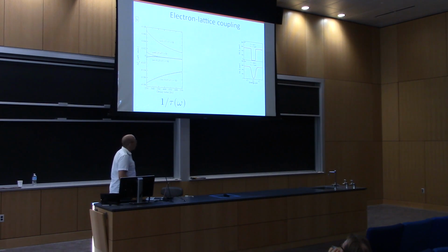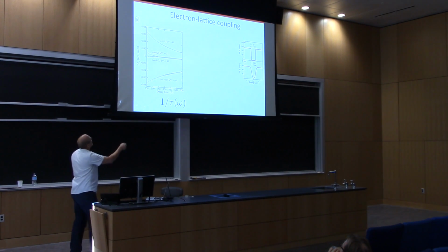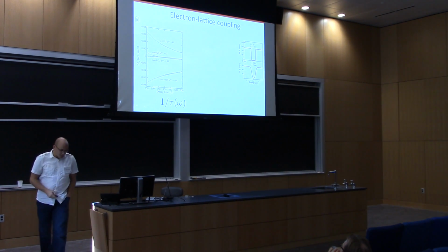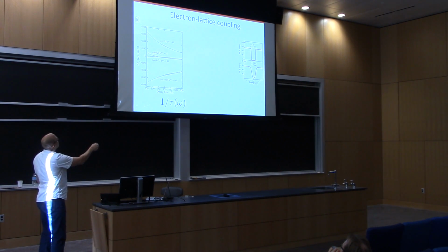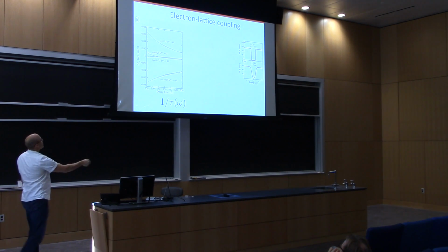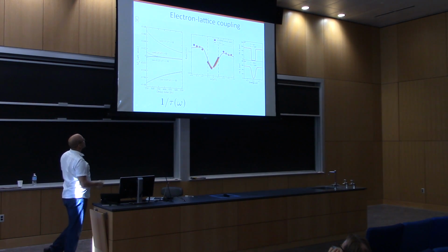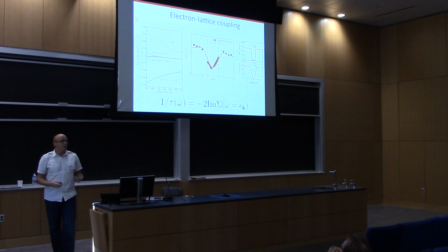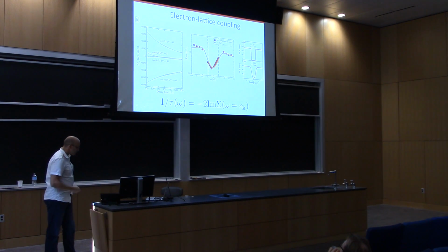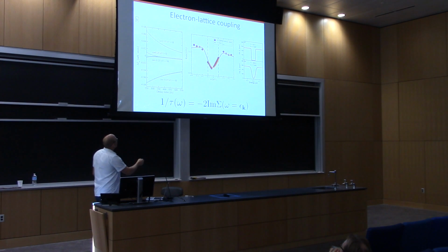And we did some work where we looked at time traces of momentum-integrated ARPES and saw that stuff inside the phonon window went much slower than outside. And that reminded us of this. And we made this sort of connection that Jim also made, where we could say, well, if you look at 1 over tau, as determined from these, as a function of frequency, you basically get the imaginary part of the self-energy.